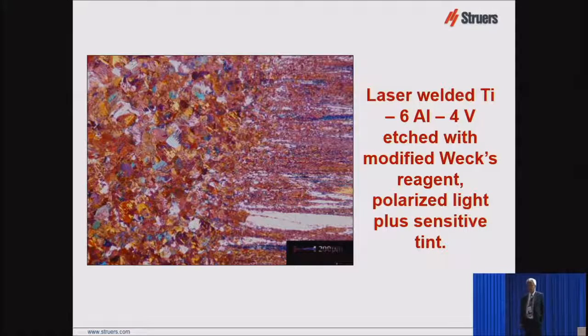And I had a close friend in Kraków, Poland, Janina Radzikowska, who was a metallographer in the Foundry Research Institute in Kraków. And I sent her an email and told her about this because I knew she worked with titanium castings. And she was a very good color etch metallographer. And she said, oh yeah, that happened to me too. She said, reduce the ethanol content to 25 milliliters and you won't have that problem. And she was right. It really worked well. So that's her etch, a very good one for titanium to do it in color.